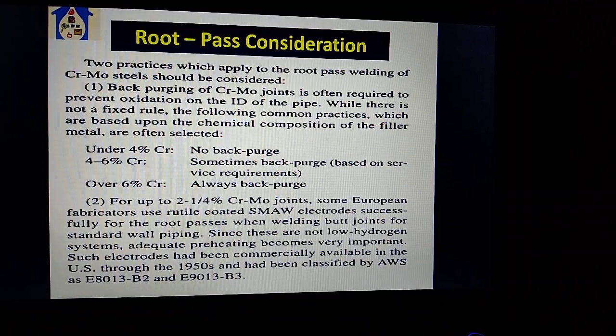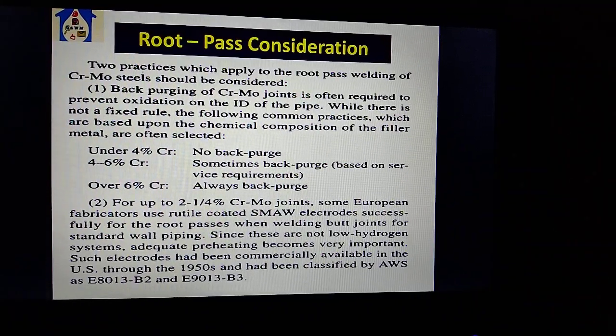Second, for up to 2¼ chrome moly joints, some European fabricators use rutile coated SMAW electrodes successfully for the root pass in welding butt joints for standard wall piping. Since these are not low hydrogen systems, adequate preheating becomes very important. Such electrodes had been commercially available in the US through the 1950s and had been classified by AWS as E8013-B2 and E9013-B3.